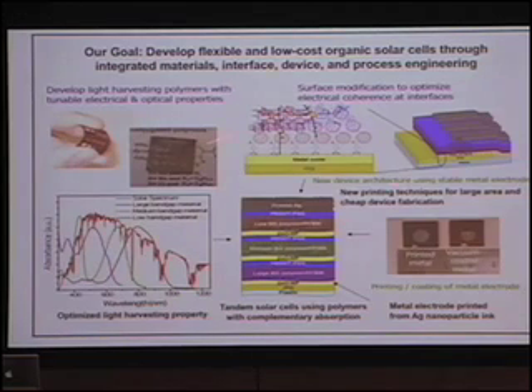And also we utilize a self-assembled monolayer, for example a C60-containing SAM, and utilize this to serve as a very good interface to collect your electrons. As a result, you can improve the selection of your charges. And with different printing or coating processes, you can take a very stable metal and do a printing process to generate your corresponding cathodes or anodes. And at last, in order to really improve the efficiency of your solar cells, we can take materials with complementary absorption, then stack them up as tandem solar cells. So you can minimize their footprint, but increase their efficiency.